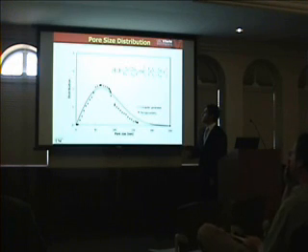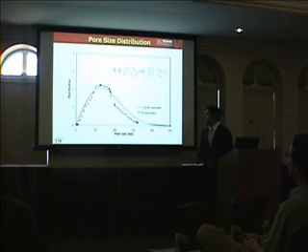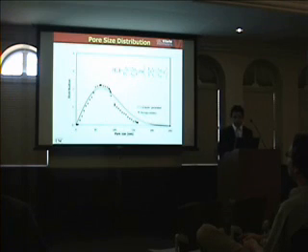So before we start, we have to have the right pore size distribution for this model. This is the equation that we use for the pore size distribution, which generates the continuous line here, and it matches pretty well with our experimental data, which we obtained for the support through the porometry technique. So this is the initial pore size distribution that we have, and it's for the support. So the membrane hasn't formed yet.